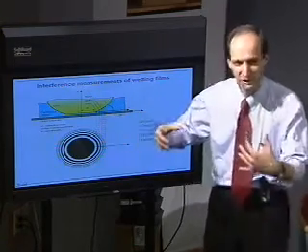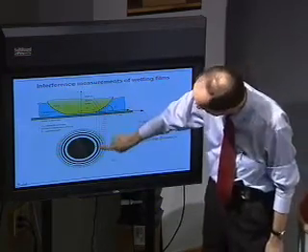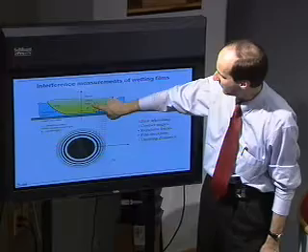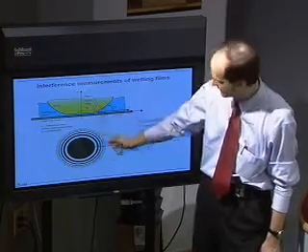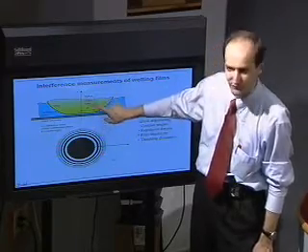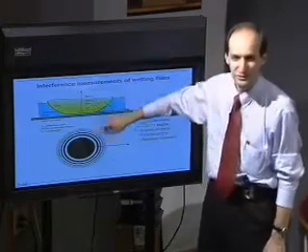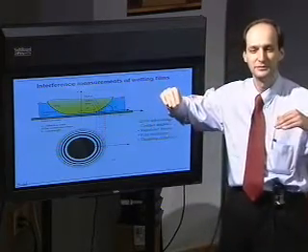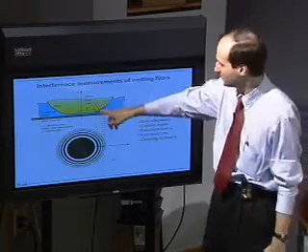So this actually allows you to know the thickness in the film. You can say in this position the film is lambda over 4 times the refractive index. In this thickness it's 3 times lambda over 4 times the refractive index and so on. So this allows you to reconstruct the profile of the interface and measure the thickness.